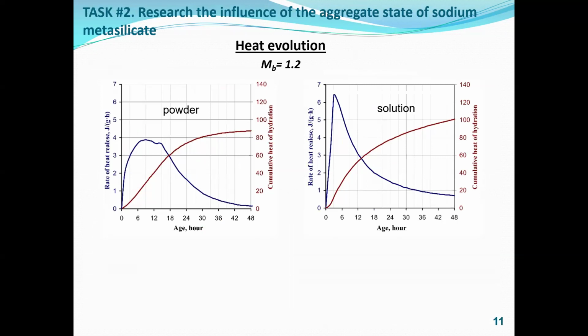Task 2. Research the influence of the aggregate state of sodium metasilicate. The use of sodium metasilicate solution instead of powder results in intensification of the early structure formation processes due to changes of thermokinetic characteristics. This can be attributed to the fact that in the case of powder, a certain time is required for the dissolution of sodium metasilicate in mixing water and its involvement in structure formation processes. In the case of sodium metasilicate solution, these processes occur and start to develop immediately and with a high intensity.